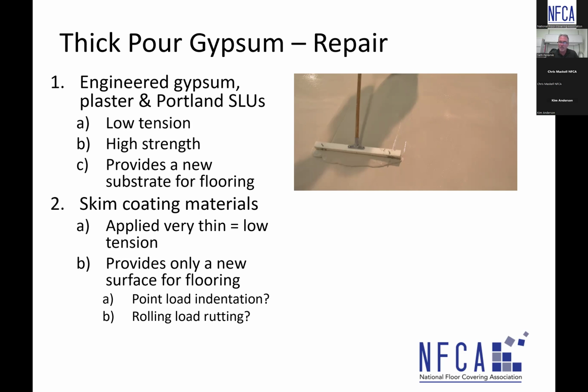Okay, we haven't changed the fact that a weaker material may lie below, and you've got to take into account any type of point load indentation that could occur, rolling loads, which would equate to rutting. Different than if you're pouring a self-leveling quarter inch over the whole floor. Now we got a quarter inch hard shell material over a thick pour gypsum that may not have the strength needed for the installation. So having that quarter inch hard shell allows everything to perform. Having a skim coat could still be subjected to point load indentation and rolling load rutting. Does that make sense?